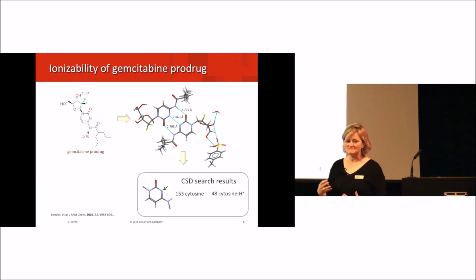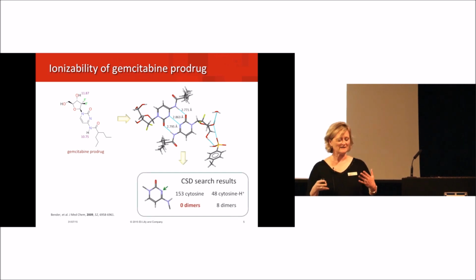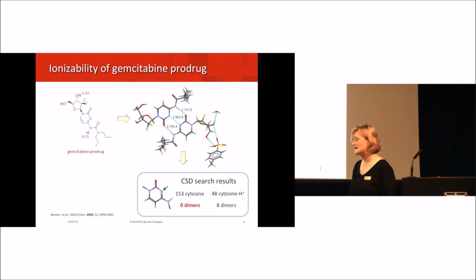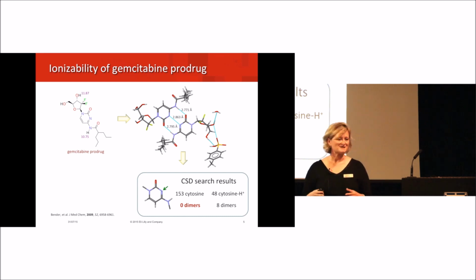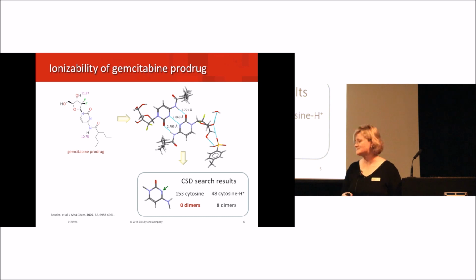And so I presented this information to my company, and it was rather controversial at the time, very contentious, in fact. So I went to the CSD because I needed the confidence that I know what I'm talking about, and that I have the backing of the CSD in what I'm saying. So I simply did a search of cytosine structures and found 200 structures. This was more than a decade ago, by the way. And out of the structures, a quarter of them had protonated cytosines, and three-quarters of them had neutral cytosines.